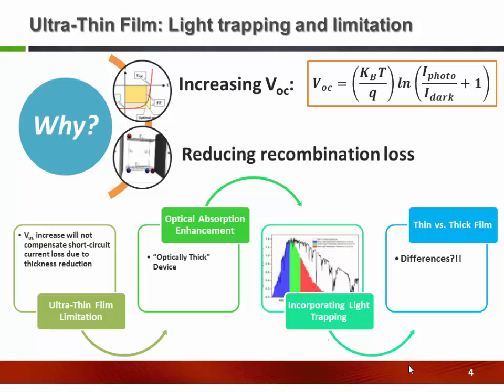The motivation behind ultra-thin film is that, by reducing the thickness of the thin film, specifically for silicon solar cells, we are increasing the open circuit voltage, due to reducing the recombination centers and the recombination rate. We could have better performance, but we have a big problem. At the same time, when we are reducing the active side of the device, we are reducing the absorber performance. Actually, the absorption is also reduced. So, we are looking for a concept that gives optically thick but physically thin devices. That's the motivation behind the application of different light trapping techniques.